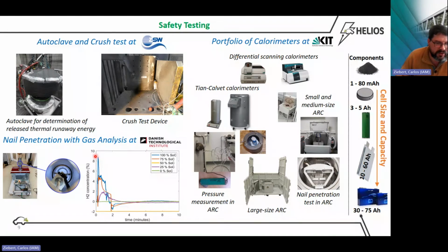So in this case, for example, we see here that for all SOCs that are higher than 0%, we see a significant concentration of hydrogen when this nail penetration is leading to different reactions in the cell and gas formation.